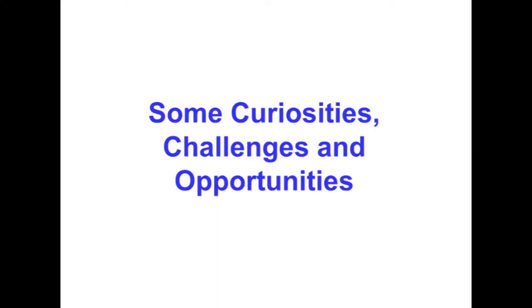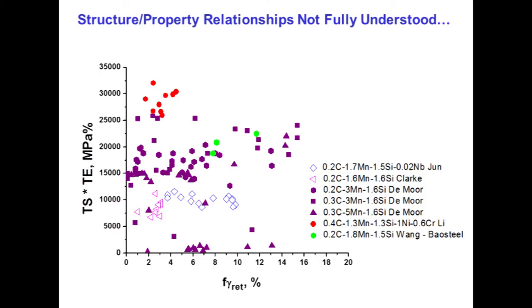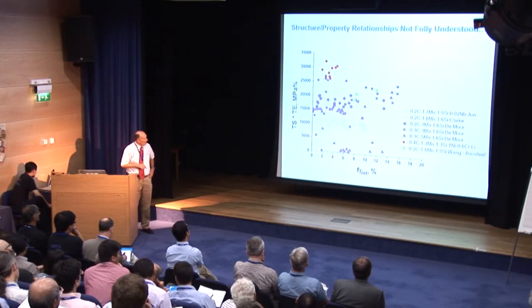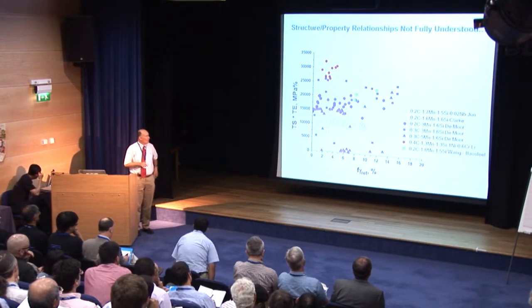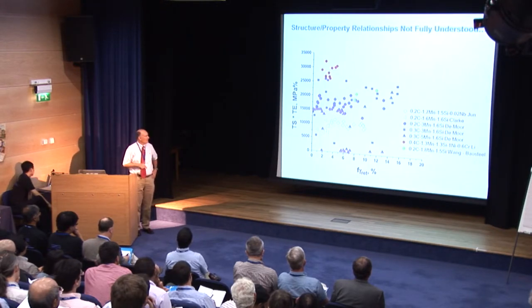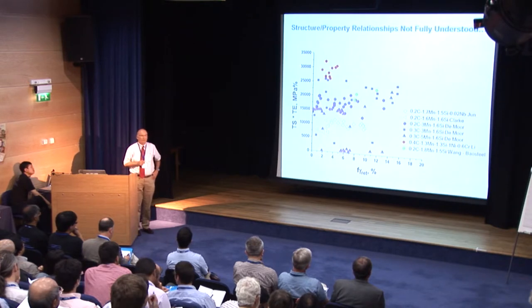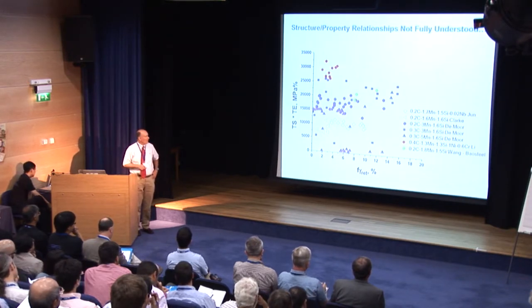So in the few minutes that remain for my presentation, I thought I'd present some curiosities, challenges, and opportunities. We've learned a lot over the last 10 years, but there are still a lot of things that we don't understand, and hopefully this community will come back at some future time and help. So here are Q&P property data. This is the product of tensile strength and elongation versus the amount of retained austenite. Our desire was to produce high amounts of retained austenite, but you can see from this diagram that in fact the properties are not highly correlated with the fraction of retained austenite. So I think that we still don't completely understand what controls the work hardening behavior and the property combinations in these steels.